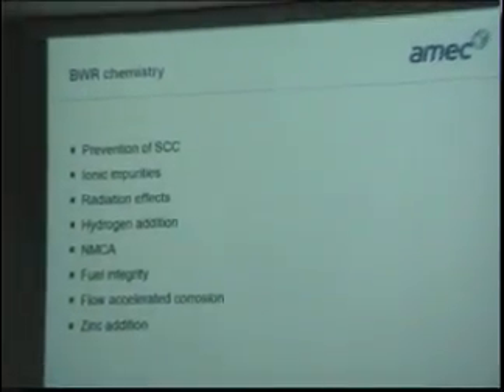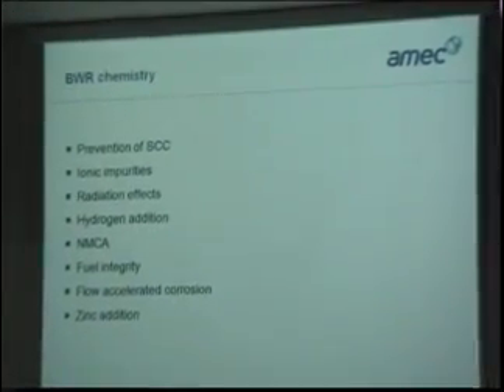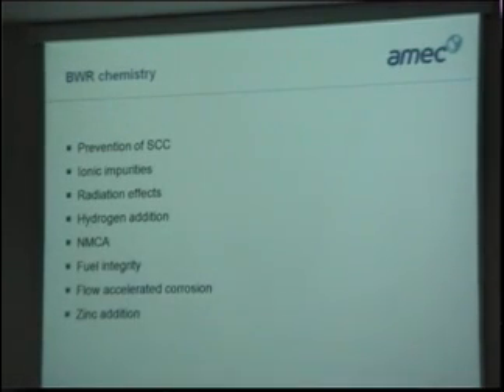because the whole emphasis on BWRs is the prevention of stress corrosion cracking. If you've got components in there under tensile stress, there's a potential for chloride-induced stress corrosion cracking because of the inbuilt tension in the component. That's the ionic impurities. There's radiation effects. We're going to talk about a bit of hydrogen addition and a process called noble metal chemical addition. And then if we've got time, a bit on fuel integrity and flow accelerated corrosion.